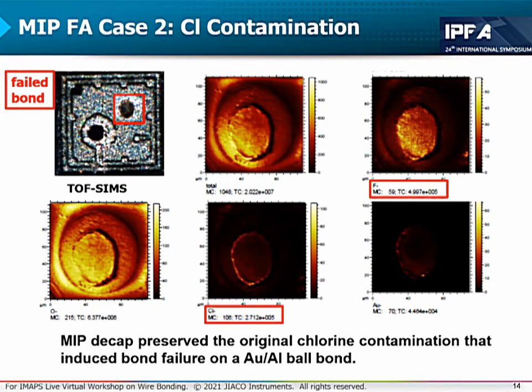To solve this dilemma, MIP was applied to decapsulate failed samples, and the outcome was the same as after acid decapsulation. Again, the bond lift occurred at the exact same location, and the other 3 bonds were intact. TOF-SIMS analysis revealed that the chlorine amount on the failed bond was significantly higher than on the intact bonds on the same sample, and also on samples from other batches which passed qualifications. Because MIP contains oxygen only, it could not introduce halogen contamination. The only logical conclusion is that these abnormally high chlorine levels originate from the sample itself.